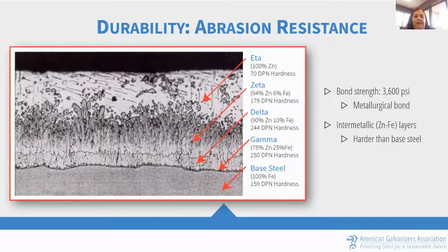And this photomicrograph is showing that basically the layers of the galvanized coating are a combination of zinc and iron. So we're not just sitting on top, but we're now intermeshed with the steel itself. And that provides great bond strength, and hardness of the coating is actually harder than the steel itself. So very difficult to damage, very difficult to hurt the coating or cause any sort of damage that would allow the underlying steel to be exposed.